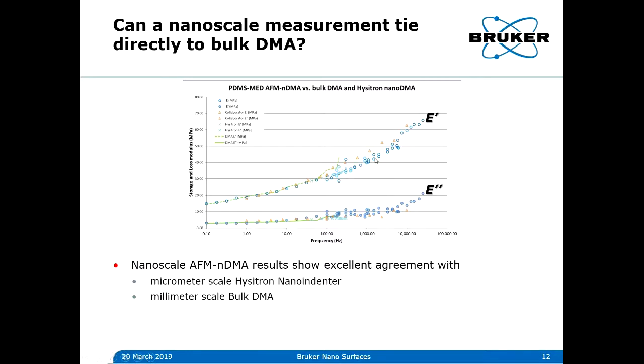The blue circles are AFM-nDMA measurements collected in Santa Barbara, and the orange triangles are collected on a different system with a different user in a different lab. So we're getting very consistent results, even without using any reference samples other than the sapphire that Dalia mentioned in order to calibrate the deflection sensitivity.